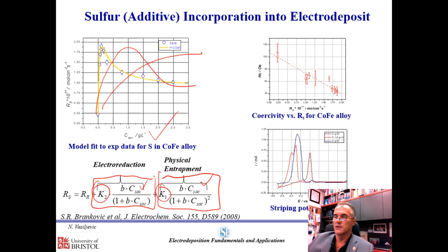In that case, you're not sure because the relation is just not so obvious. Yet if you recalculate your sulfur content in the deposit or incorporation rate of sulfur, and then you plot the coercivity with respect to that, you will see that this is basically a straight line. So more sulfur from the additive directly contributes to the formation of the softer magnetic deposit, and the sulfur from the deposit incorporated into the lattice creates this amorphization, which is good for magnetic softness.